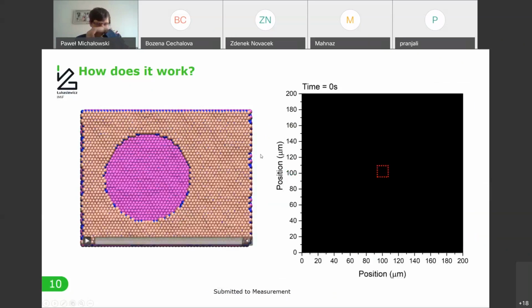Okay, so now there is also a question. I showed you how I can remove the top layer without damaging the second one. So the question was, how does it work? And for that, I cooperated with my friends from Krakow, who make computer simulations. And from their simulation, it turned out that for a sample which is a perfect hexagonal boron nitride layer, for experiments with such a high incident angle, which was, I think, 70 degrees, their simulations showed that all projectiles are simply reflected from the surface, and there is no sputtering process at all.